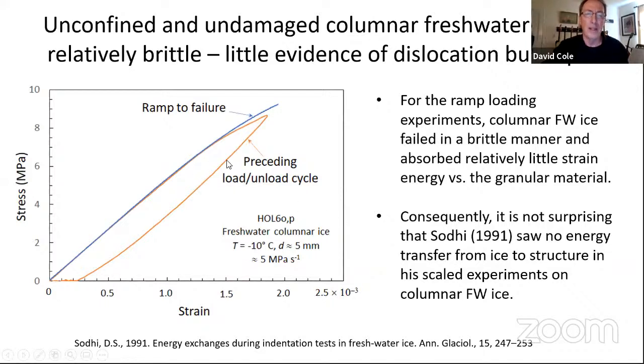This is just an example. Just the cycle before failure with columnar freshwater ice, you really get these tiny little hysteresis loops, not much energy being absorbed. The very next cycle, it just ran up to failure. And you just don't get the anelasticity out of that material that you do out of columnar or granular freshwater ice. So in experiments such as Sodhi's on columnar freshwater ice, you just won't get the kind of inelasticity buildup before failure that you get in other ice types. So it's not surprising that he didn't see any energy input back into the structure in his scale model experiments.